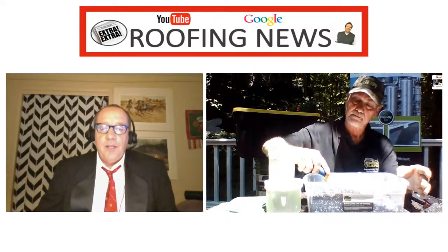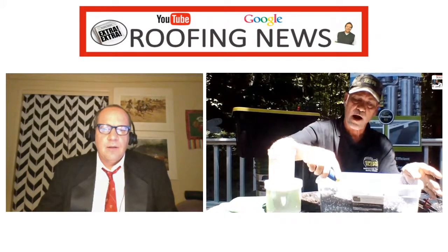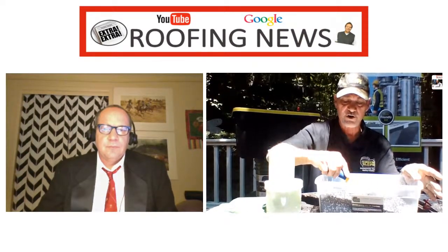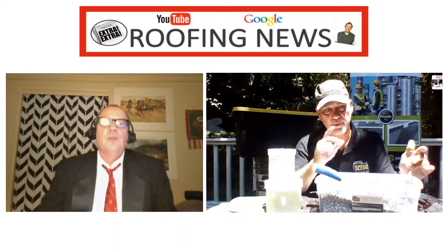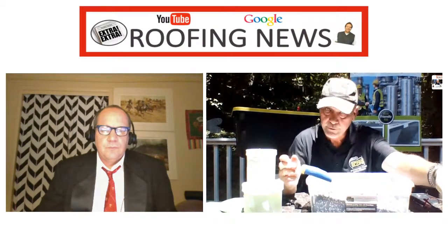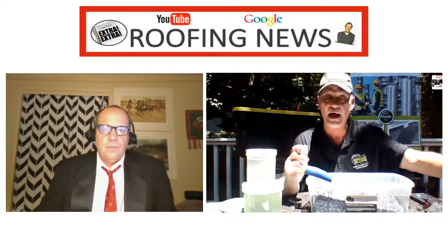Is it like concrete? You need to let it set for 24 hours or so? We have 24 hours in our recommendations, just because it's a moisture cured product that can take anywhere from 2 to 6 hours to set up, depending on how thick it is and the weather. If it's a nice sunny day like today, or if it's cloud covered, colder in the winter, it's going to take longer to cure.